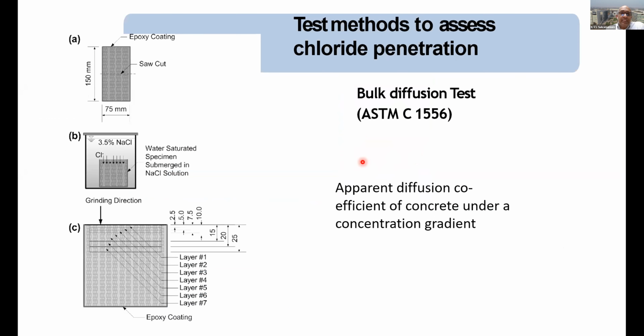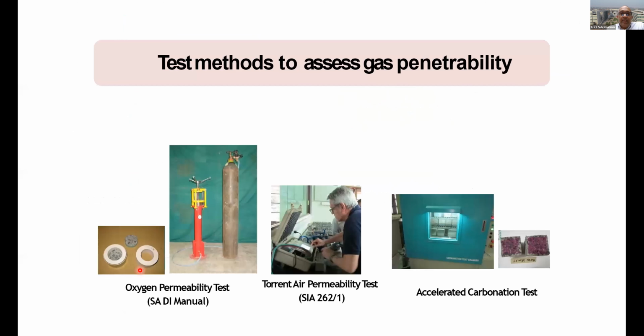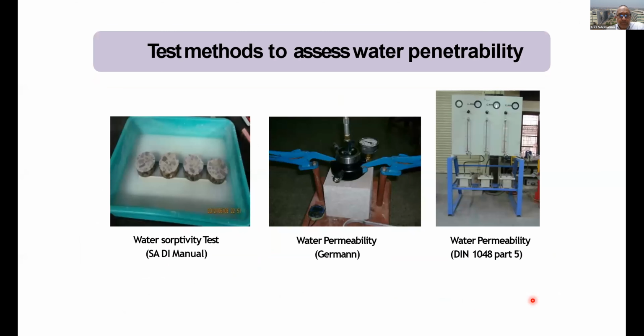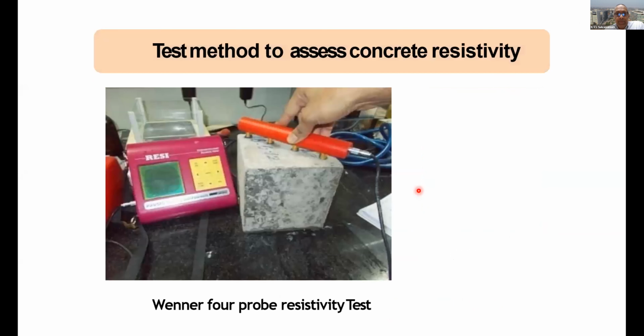We have similarly other methods to assess chloride penetration. There's a diffusion test that measures how fast chloride ions can diffuse through concrete. There are gas penetration methods like oxygen penetration or the air permeability or the accelerated carbonation test, which tell us how fast any gas like carbon dioxide can move through concrete. And there are methods of assessing water permeability, because if water can get in through concrete, then again, steel will start corroding. So there are ways of assessing that for concrete. And these are all accelerated tests that give us results in a matter of minutes or hours.